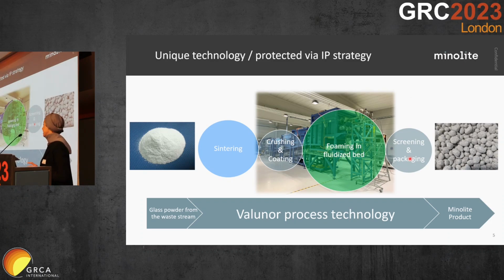What we are doing is that we are milling the glass waste to powder, and we are adding some additives, and then we are doing the sintering process, and after that crushing and coating, and then expansion or foaming in a fluidized bed. And you can see a picture of our expansion kiln in the back. And then we will have screening of the final product and packaging. And you can see the final product here.